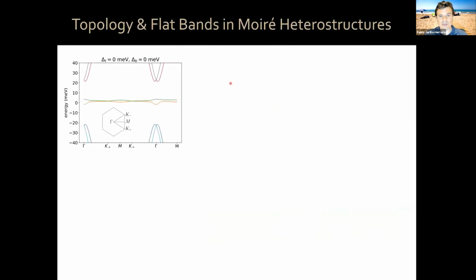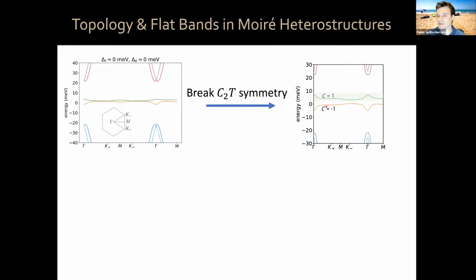Now, I'm going to mention only a few words about this, but these are the bands of magic angle twisted bilayer graphene. There are several sets of bands here, again because of the valley degeneracy and sublattice degeneracies too. So you have these degenerate bands, which are not gapped, and they're very flat. Turns out, if you break C2T symmetry, where C2 stands for 180-degree rotation around the Z-axis, an axis perpendicular to the graphene plane, and T is time reversal symmetry. If you break the product C2T, then these flat bands become gapped, and these have different Chern numbers.